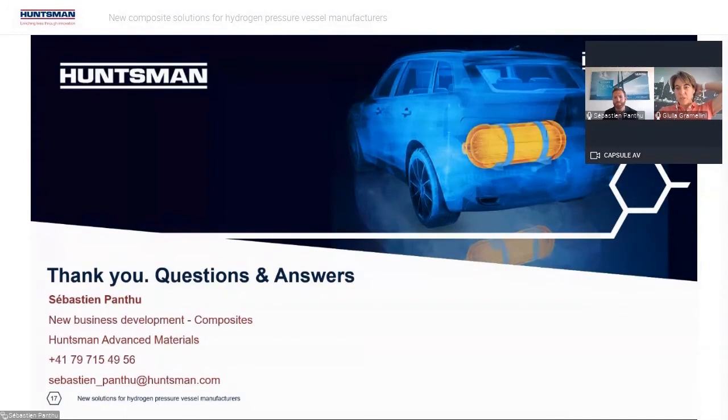Thank you. Another question: do you have some requirements or hints concerning the pretreatment needed for the liner, especially for type 4 pressure vessels, to enable the bonding between plastic liner and reinforcement? Of course, bonding thermoplastics is never an easy task. In this case, you can use surface treatment, you can use primers, but for cost reasons, we have lots of customers working without any treatment. What is also important, just in brackets, because it's not exactly the sense of the question: when using polyamides, pay attention that you don't pick up too much humidity before winding, and a drying process is highly recommended.